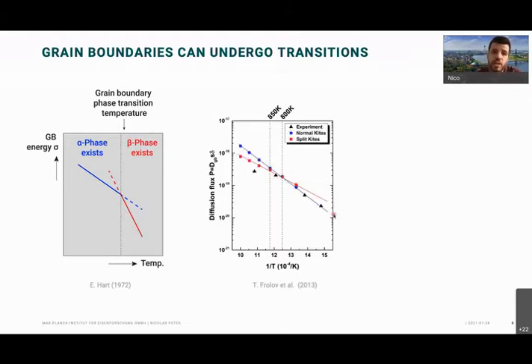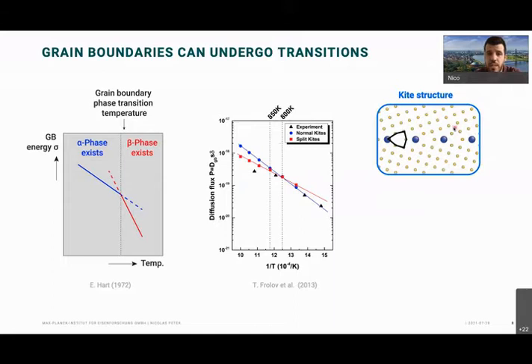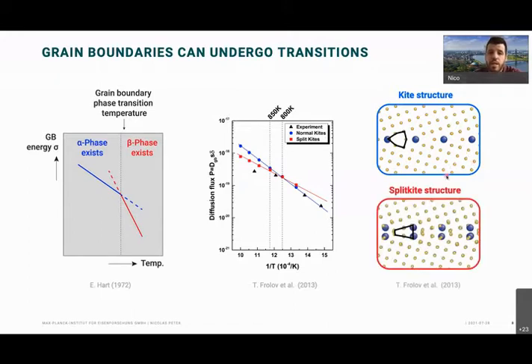So he found actually two phases that have a coexistence point. So there are two ranges where two different grain boundary structures exist, and how these look is shown here. So this is the sigma 5 grain boundary as I showed it to you before, with silver sitting at certain positions. And then there's the low temperature configuration. And then if we exceed a certain temperature, we actually form the split kite, or he called it a split kite structure, where the grain boundary structure changes. However, the plane remains the same. So this was more or less the first prominent example, I would say, where people were finding these transitions.